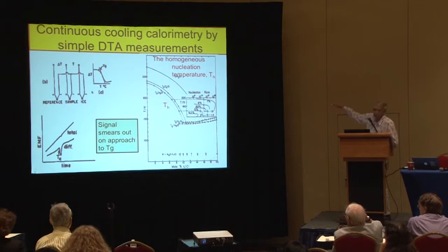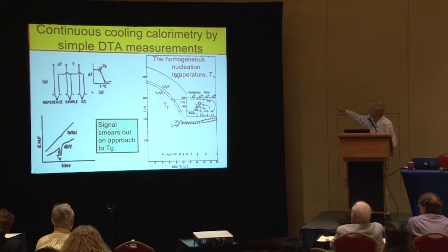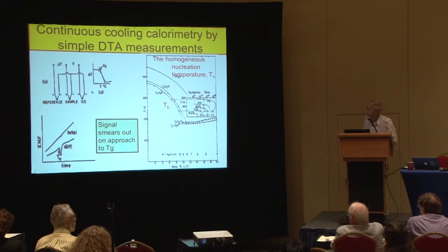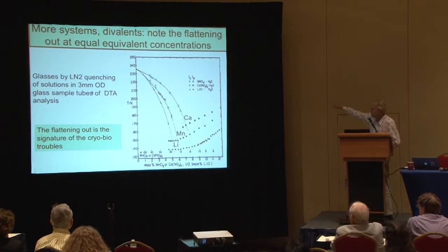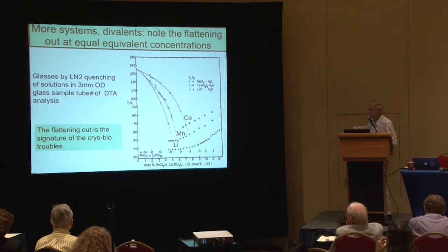And you saw one of these plots in Valeria's talk. And here's a repetition of that with some relation to the nucleation rate for the different temperatures, which I don't need to go into. So this is a nice measurement to make, very simple. And here it is for different monovalent and divalent cations, and you can do it for any system you want. We plotted here on a reduced scale to take care of the different charges of the cations, so that it looks like the glass-forming range is determined by the ability of the cations to dismantle the water structure, because it comes in here at more or less the same concentration on this equivalent concentration regime.